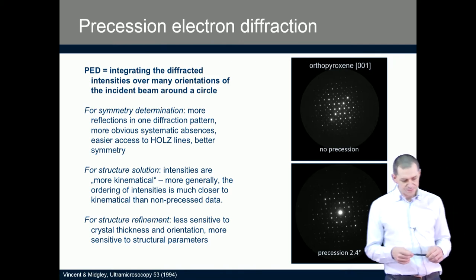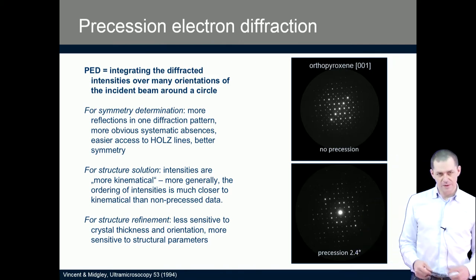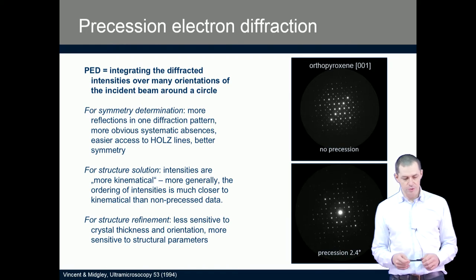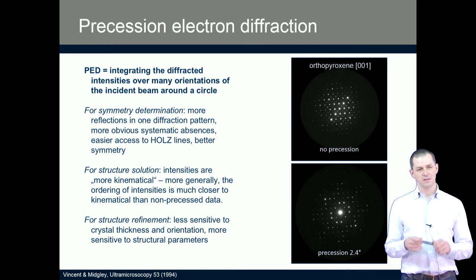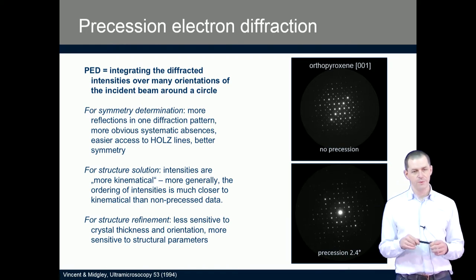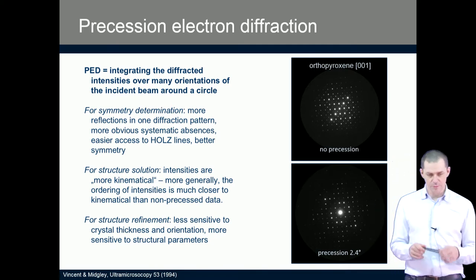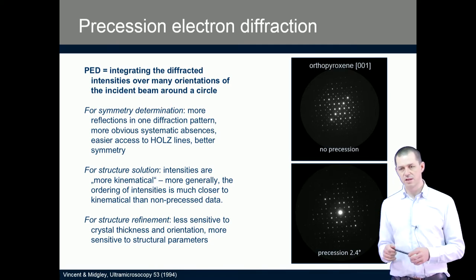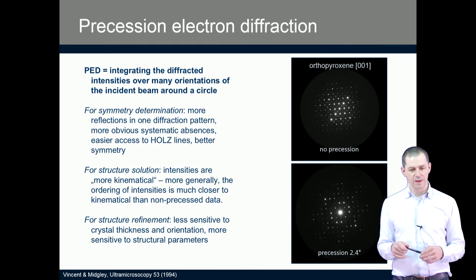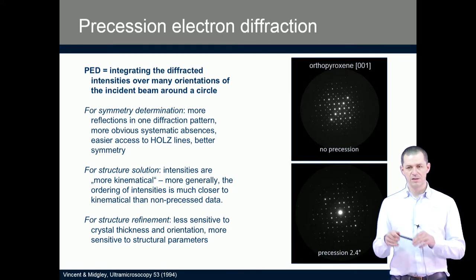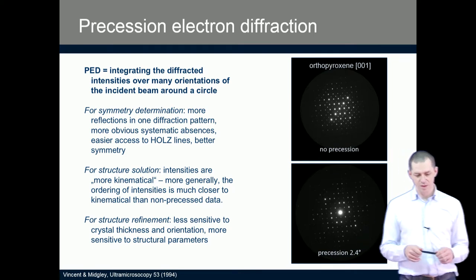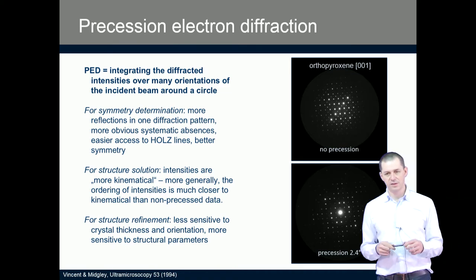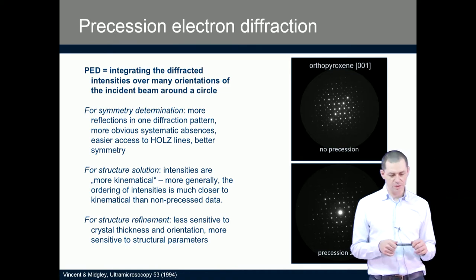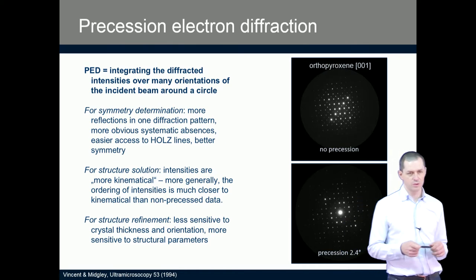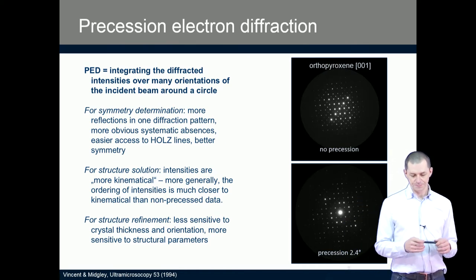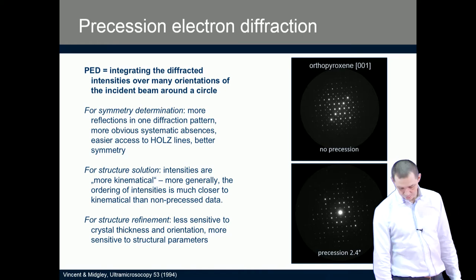And for structure refinement, the advantage is that they are also less sensitive to crystal thickness, crystal orientation and imperfections of the crystal, and they are more sensitive to structural parameters like atomic positions and atomic types, or atomic species. So for all aspects of structure determination, precession electron diffraction is a useful method.